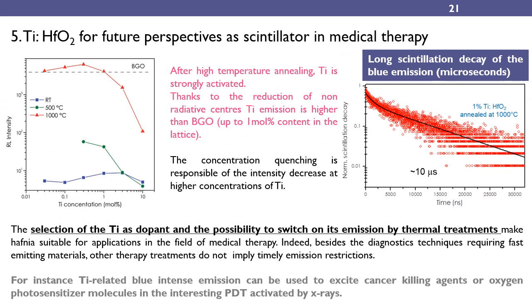The most important result obtained in the investigation of the luminescence properties of titanium-doped hafnium oxide under X-ray excitation is the achievement of highly luminescent nanocrystals. In fact, the strategy of doping the nanocrystals with titanium has been successful. Then, the following thermal treatment procedures are able to activate the titanium centers, and the final intensity of the blue emission after annealing at 1000 Celsius degrees is equal or even higher than the BGO intensity for content up to 1 molar %.